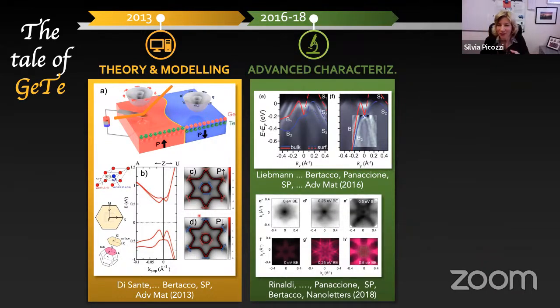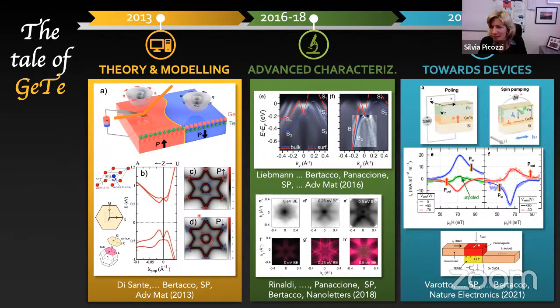And then, about 3 years after our proposal, we managed to convince some experimentalists by doing ARPES and spin ARPES. Here, of course, it's a bit complex because in addition to a bulk Rashba effect that you have in germanium telluride, you also have a surface Rashba effect. So we have to disentangle, let's say, the two effects, but the experimental result matches our prediction well. And then recently, of course, with Rashba, your dream would be to do spin to charge conversion. And so this is what my colleague in Milan tried to do with a germanium telluride interface with iron. And it seems that you can really control the spin to charge conversion by means of an electric field which is applied to your heterostructure.